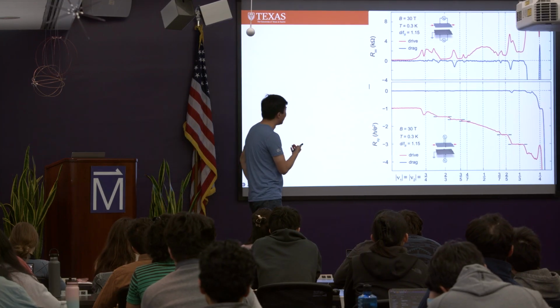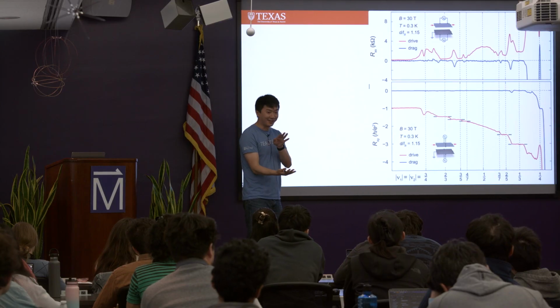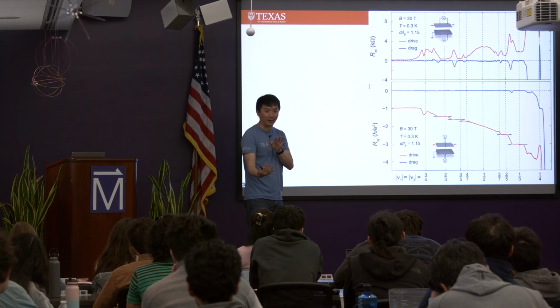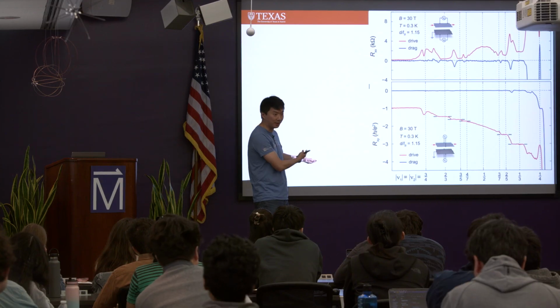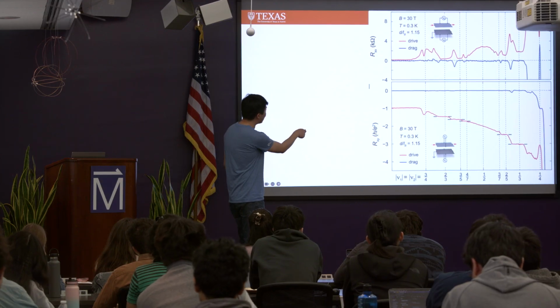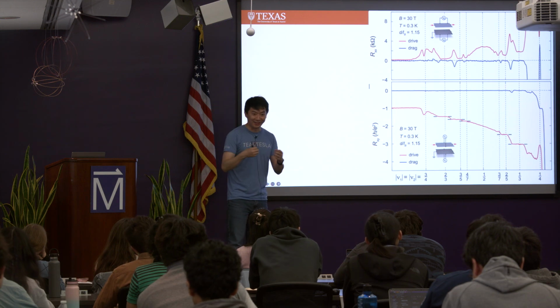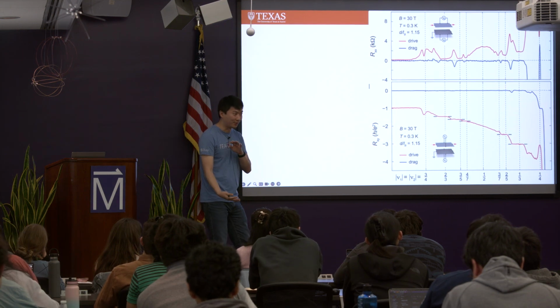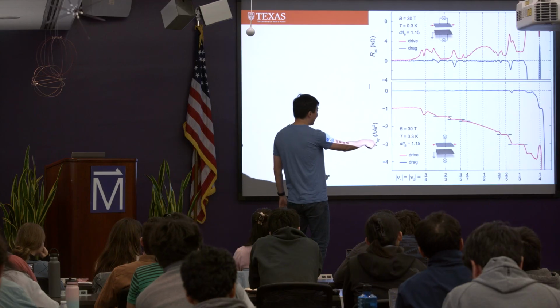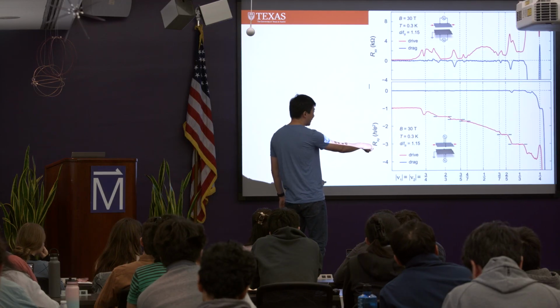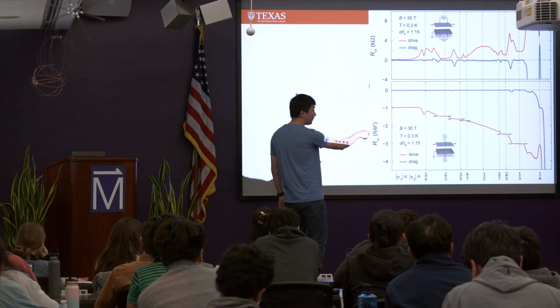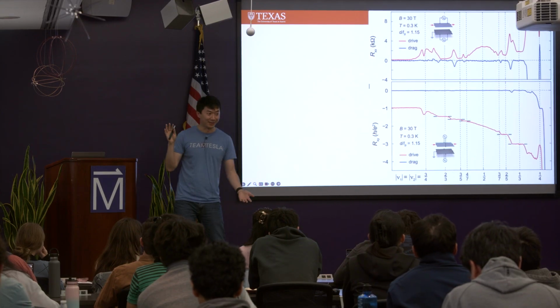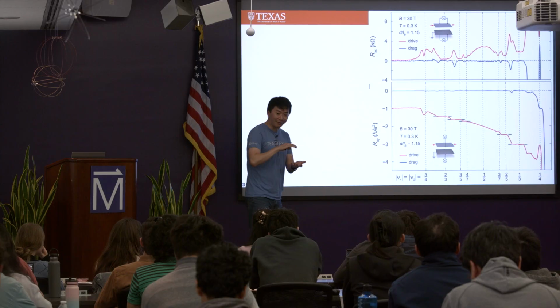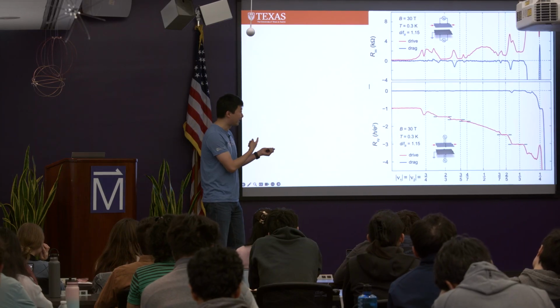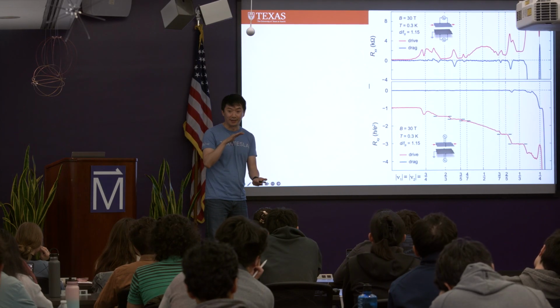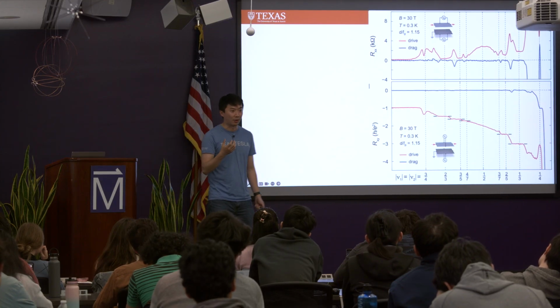The reason for that is because the interlayer separation, we intentionally make it very far away, about 7 nanometer, right? Almost double the value I showed you earlier. And we go to extremely large magnetic field so that the intralayer correlation is much stronger than interlayer correlation, right? And at the same time, for example, here you get Laughlin state in both layers. And if you look at the drag data, it's 0, right? Meaning that the two layers essentially decouple. But we do have 2 copies of Laughlin state. The drag is 0 because there's no quasi-particle in both layers, right? Because there's very robust charge gap of Laughlin state.